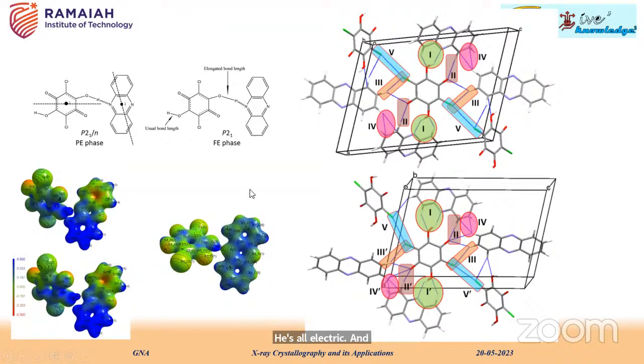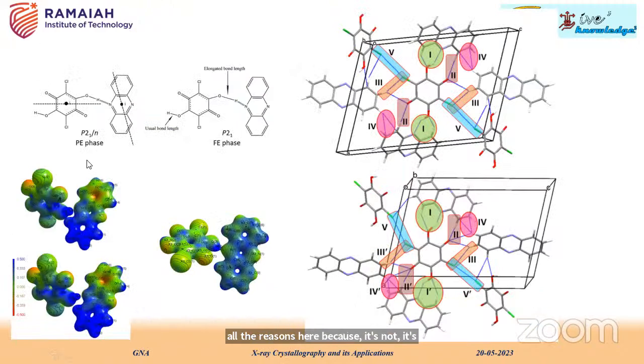Today we also have quantum mechanical techniques, and we can couple them with the X-ray diffraction technique, and understand the distribution of electrons within the unit cell. Therefore we observed that the elongated hydrogen bond is responsible for the ferroelectric phase, whereas the normal hydrogen bond is responsible for the paraelectric phase. This is also revealed by using quantum techniques and charge density analysis. I'm not able to show all the results here because it's not relevant in this case. Like this, we can use crystallographic techniques and fine tune the properties by modifying some of the parameters, and by observing different interactions, we can predict the application.